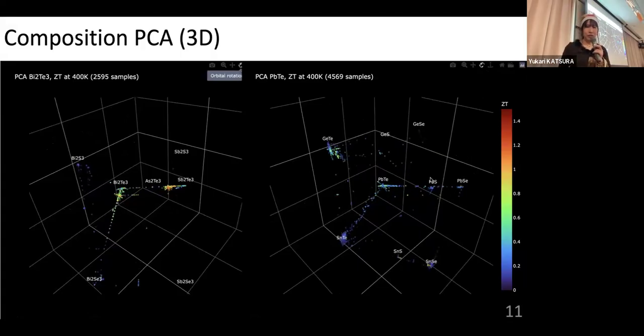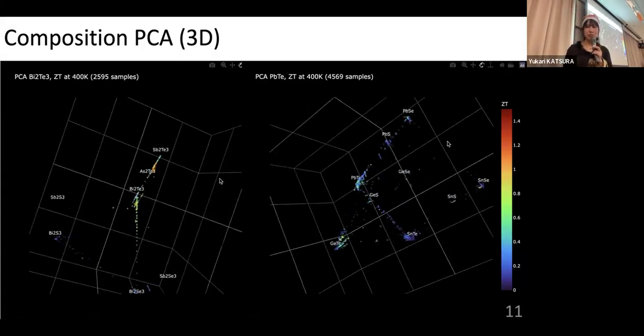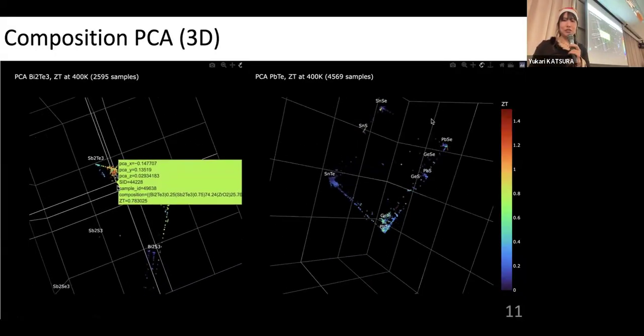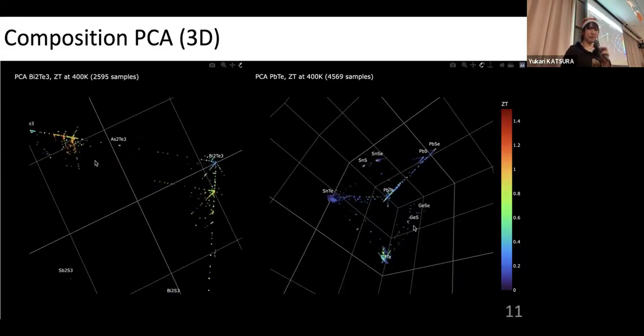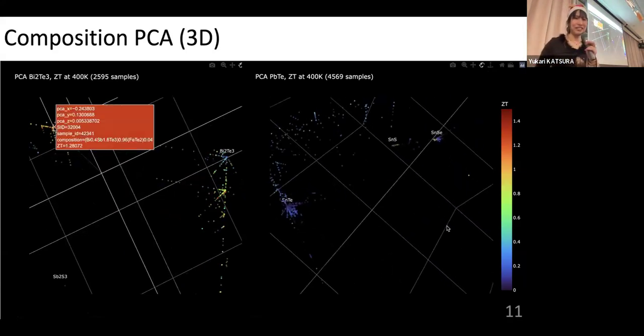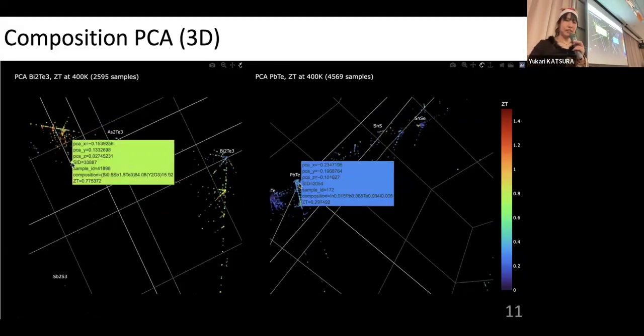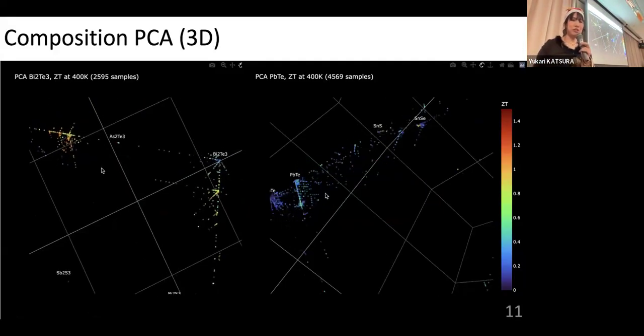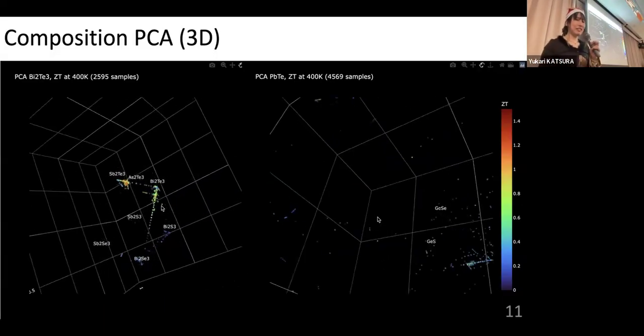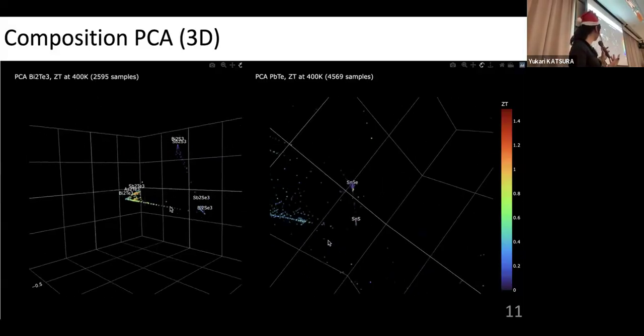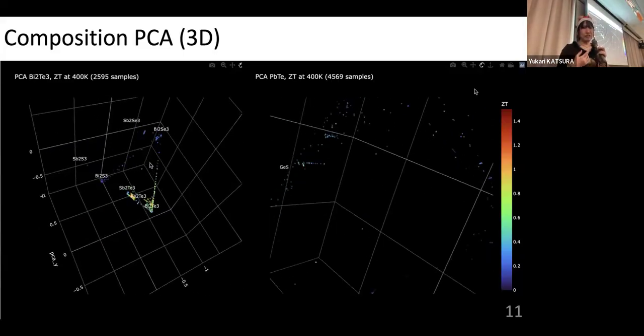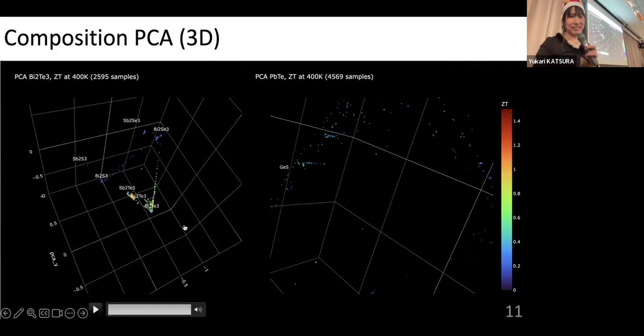So the left is the bismuth telluride related samples, and the right is the lead telluride based samples. And the colors show the ZT, which is the thermoelectric figure of merit, and higher ZT is better for application. And so we can browse the samples reported in the past and which composition results in higher ZT. And another thing we can see is that there is so much unstudied composition space. So you can see where you can try to explore. And so you may achieve better samples from this distribution. So I'm showing this plot openly online, so any experimentalists can access this and think about new ideas of research.